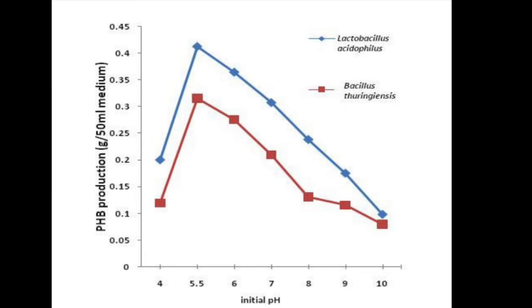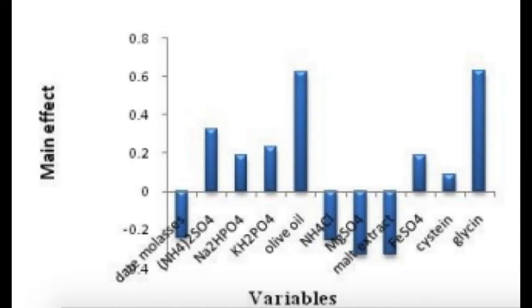The test also revealed the optimal temperature to be 37 degrees C, a pH of 5.5, and the nutrients were also considered. From the graph, it can be seen that a mixture of olive oil and glycine will give the optimal conditions for PHB manufacture. This would not be used in a large-scale production of PHB, as olive oil is expensive. Instead, glycine would be used.